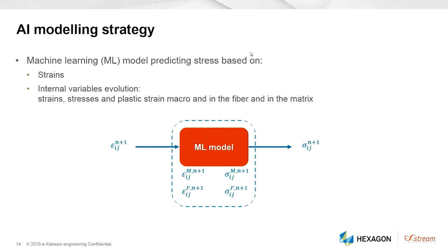The modeling strategy consisted of predicting the stress based on the applied strain, as well as a series of internal variable evolutions, namely strains, stresses, and plastic strain, both macroscopic and in the fiber and inside the matrix.